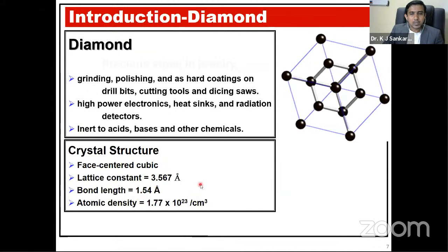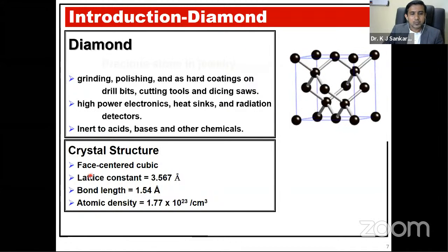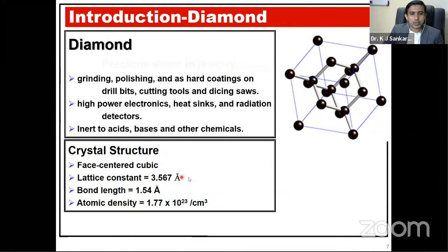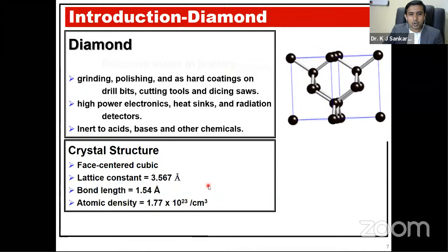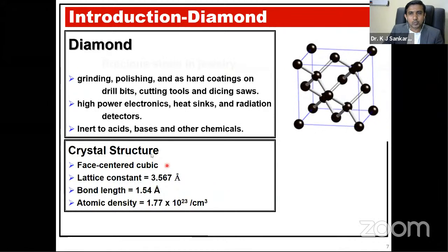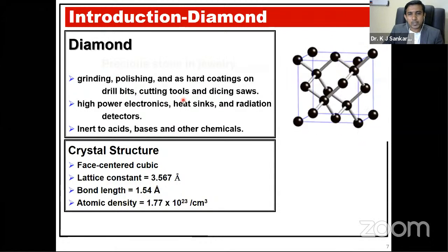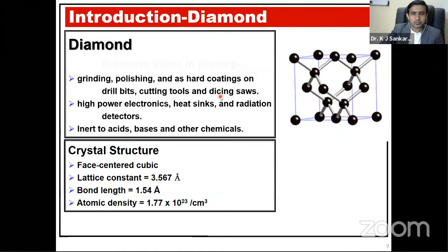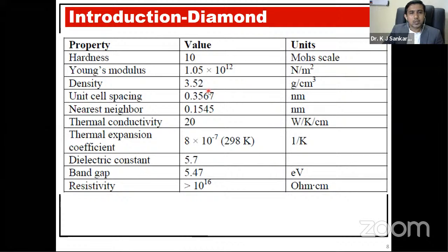So this is the crystal structure of diamond, and you can see the animated one of the diamond, which is a face-centered cubic structure with a lattice constant of 3.5 angstrom, and it has a very good atomic density of 1.77 × 10²³ per centimeter cube. Because of this very high atomic density, it is the hardest known material. And here I introduce some of the properties of diamond. I mentioned this is the hardest known material, and especially for the electronic applications, I need to focus on the band gap and the resistivity. So the band gap of diamond is 5.47 eV. So it's a wide band gap material. So you can see it's very difficult to conduct electrons through the diamond material because of the wide band gap. So you can see the resistivity is really very huge, greater than 10¹⁶.